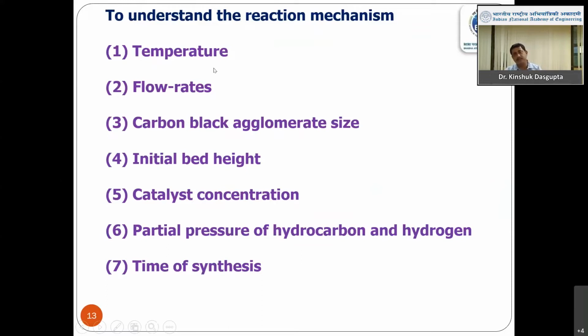So from temperature we can understand the activation energy. Then by changing flow rate, we can understand whether it is a diffusion control, this is the external diffusion control. By changing the carbon black agglomerate size, we can understand the internal diffusion control, because when we change the size, the pore size and pore diffusivity change, so the effect will come. Then we also change the initial bed height, that also gives the internal diffusion. And the catalyst concentration and partial pressure of hydrocarbon and hydrogen show us whether there is a chemical reaction control or not. And finally, time of synthesis shows whether there is any deactivation of the catalyst or not, because it is a catalytic activity and there is always a tendency that the catalyst gets deactivated. So we can understand the kinetics of deactivation by studying the last parameter.